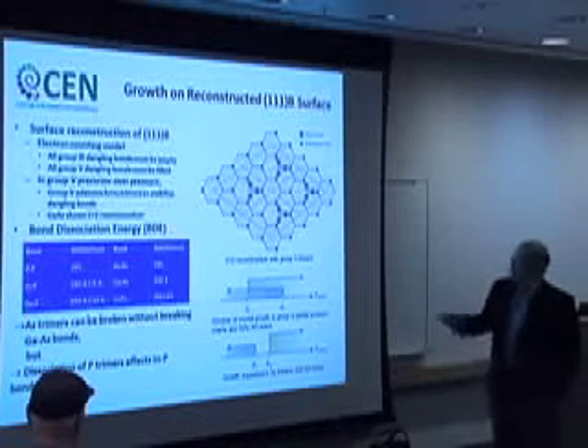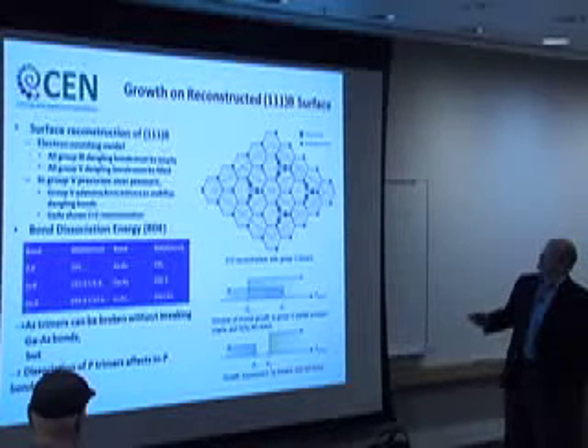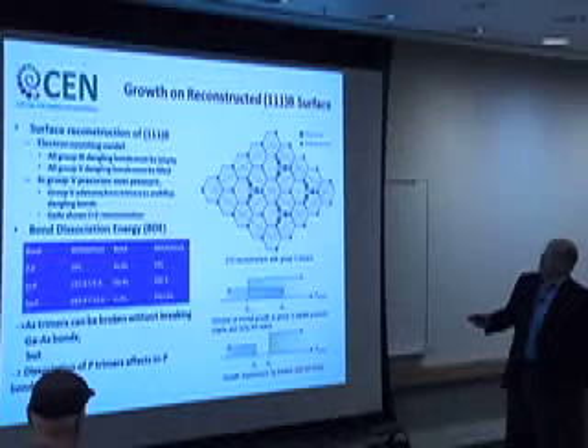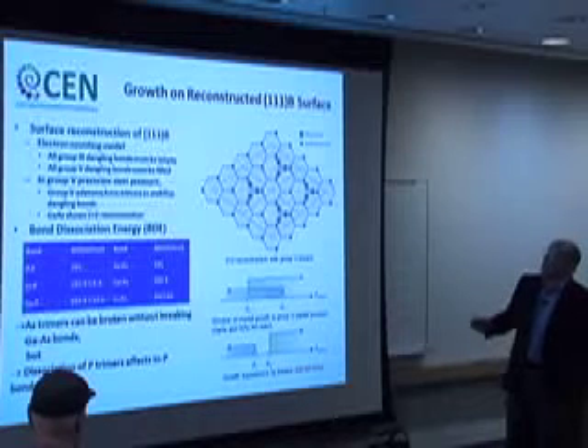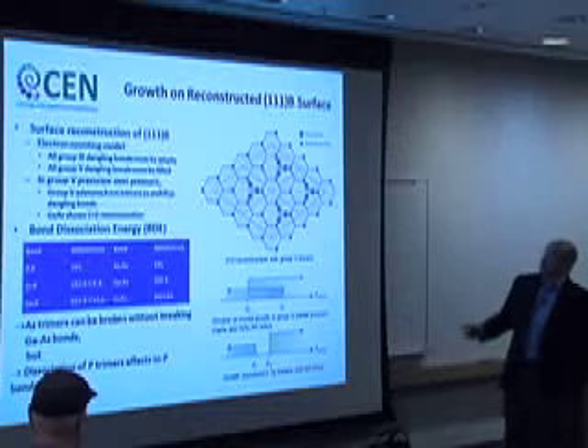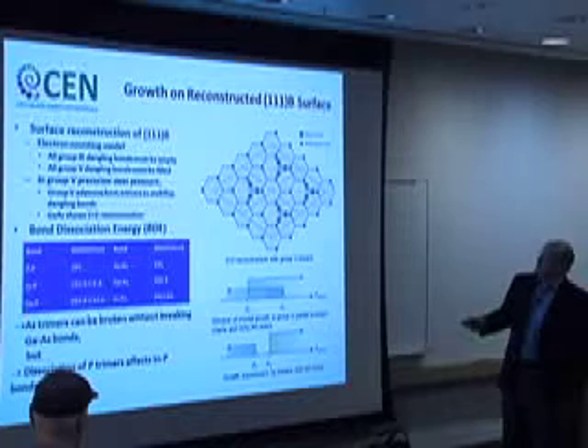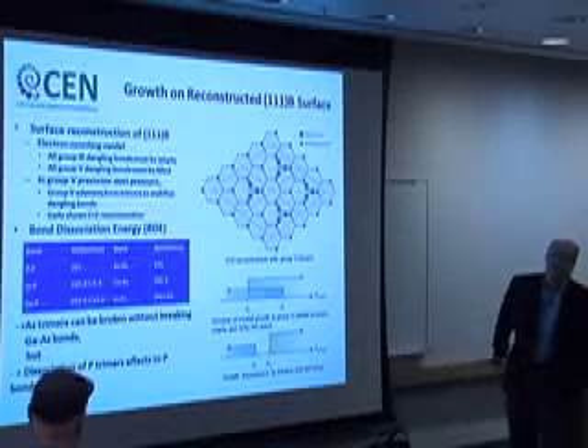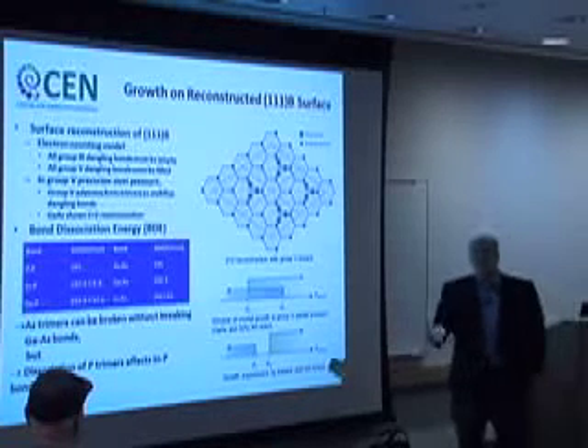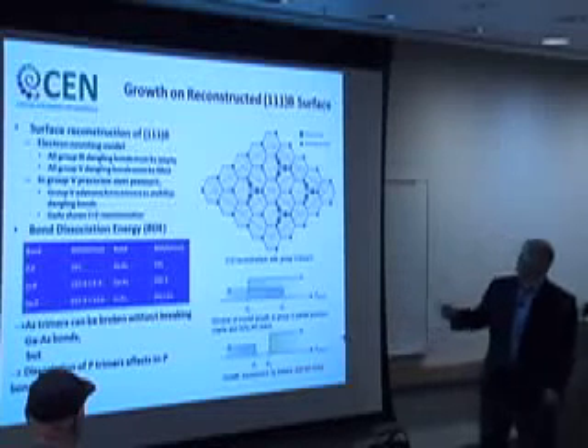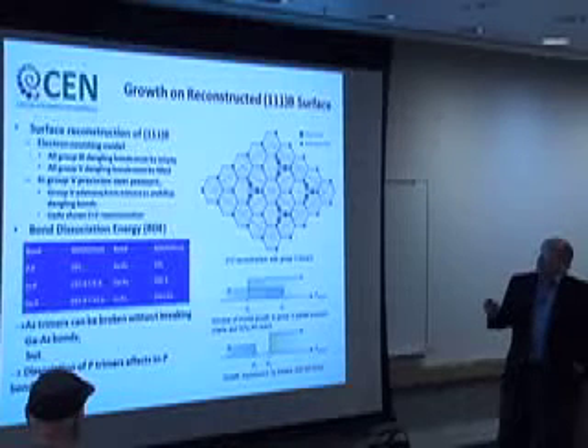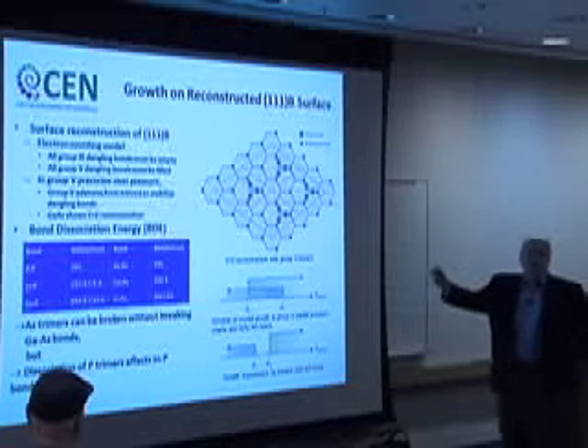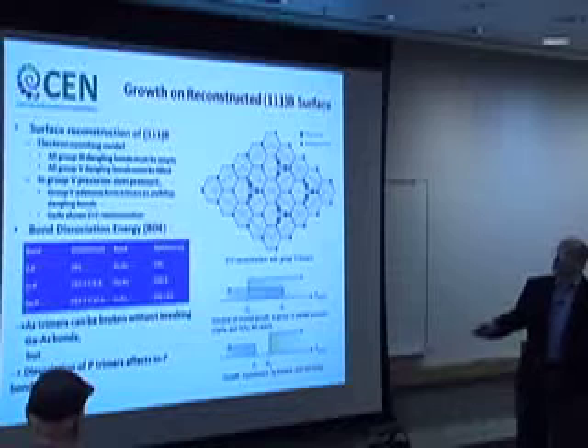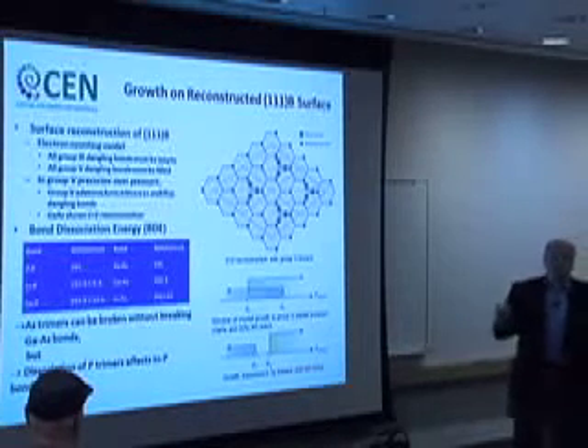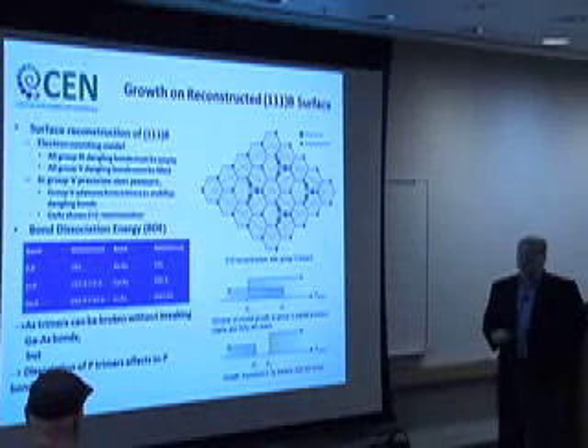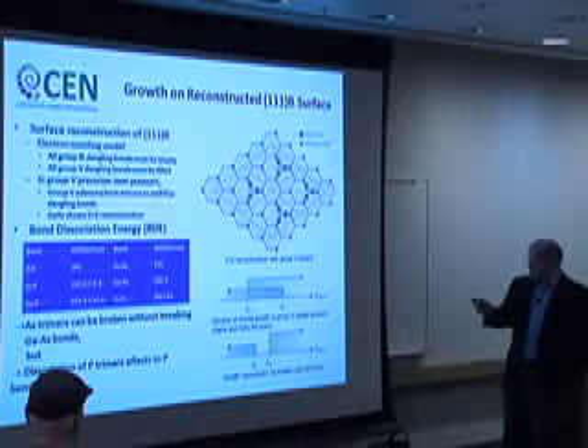So our simplistic explanation of this is that when the surface gets reconstructed in the growth of indium phosphide, whatever we do to break these phosphorus-phosphorus bonds in order to let indium adhere to the surface and grow another monolayer will be sufficiently aggressive that it will also attack the indium phosphide bond. And so we get into a situation where we can't find the right conditions in order to grow indium phosphide. Now, this is fragmentary evidence, but it is the only case for which these bond dissociation energies are ordered the way they are, and it's the only material that won't grow as a nanowire on the 111B orientation. And so we think that's strong evidence that that's what's happening in this particular material system.